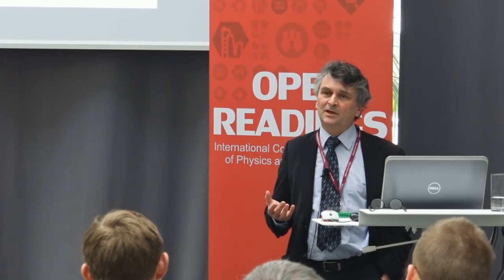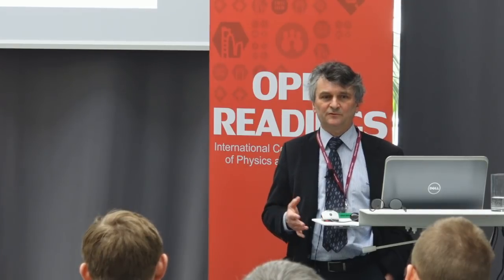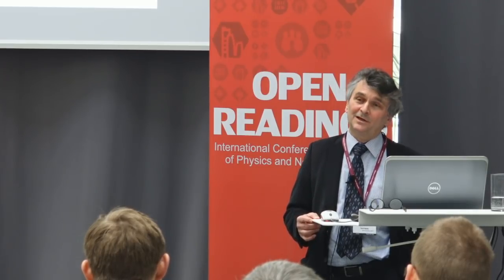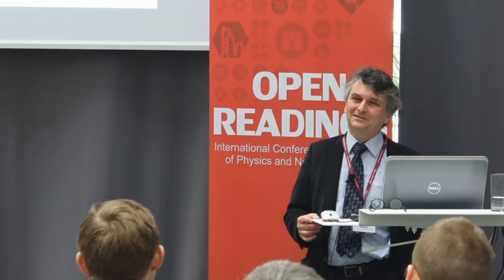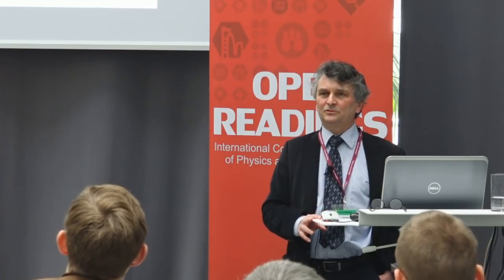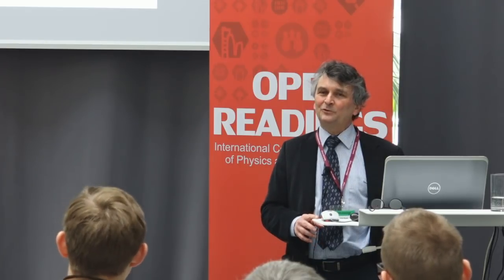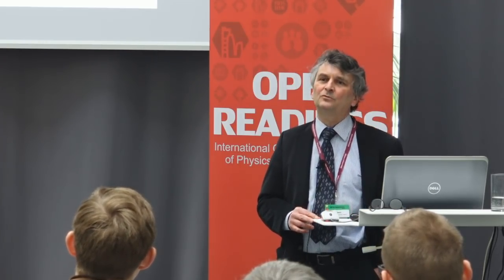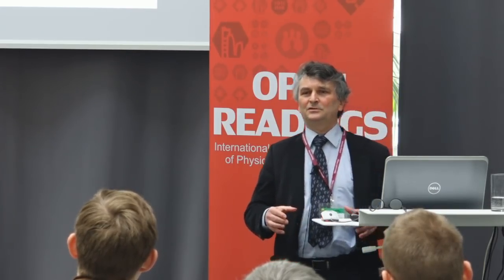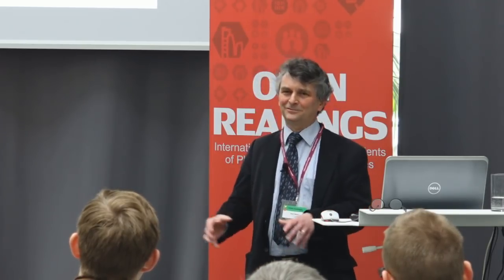To come back to the silicon germanium, the most spectacular result came from MIT perhaps 5, 6, 7 years ago. Jürgen Michel at MIT reported an electrically pumped laser based on germanium on silicon. And the trick is indeed that by going to very, very high doping on one hand, and also by going to rather extreme straining of the semiconductor, you can bring germanium just about to the transition from indirect to direct.